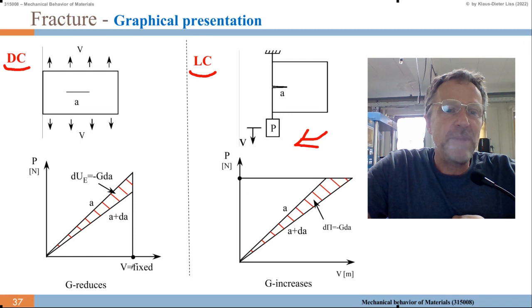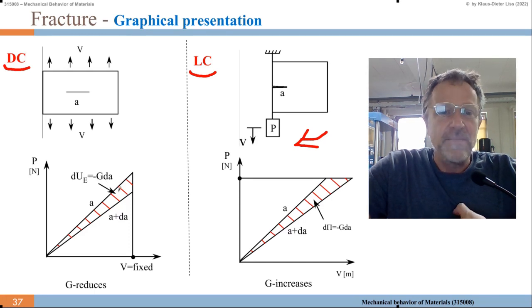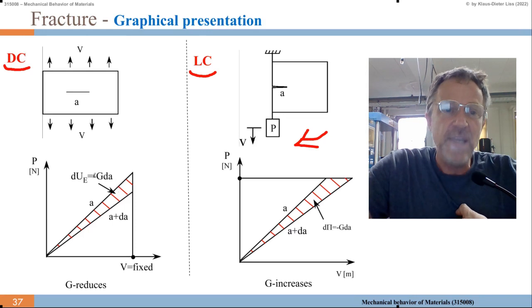Not so in displacement control. There, I hold the volume fixed at this value, but I grow my crack from A to dA. Then I have dU over dE becomes minus G times dA, and G reduces. G has to reduce to keep the volume constant. So here the G reduces, and there the G increases.